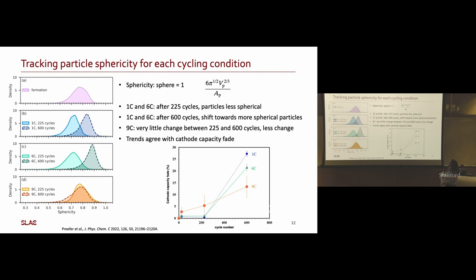Okay, we also could track sphericity. Sphericity is basically how spherical something is. A perfect sphere is one. So anything less than a sphere, which all of this is, is less spherical than a sphere. So we start out with something pretty spherical, and we're moving towards things being less spherical after 225 cycles, and then they move to more spherical after 600 cycles, except for 9C. 9C, the damage is already done between 225 cycles and 600 cycles. There's not much change. And so what is going on?